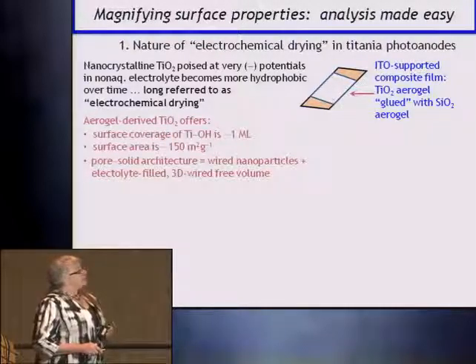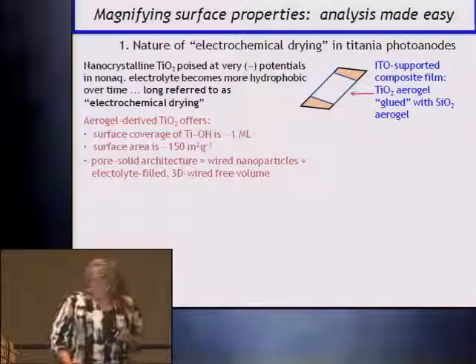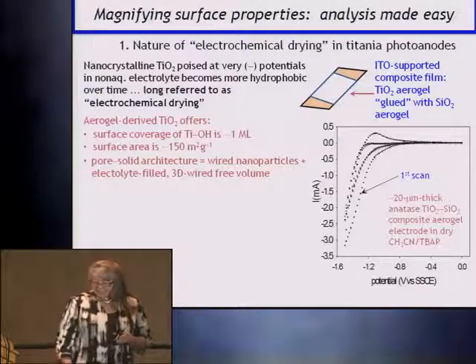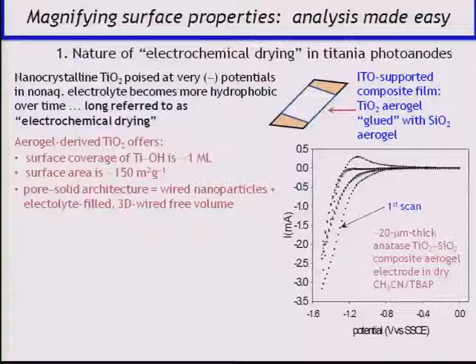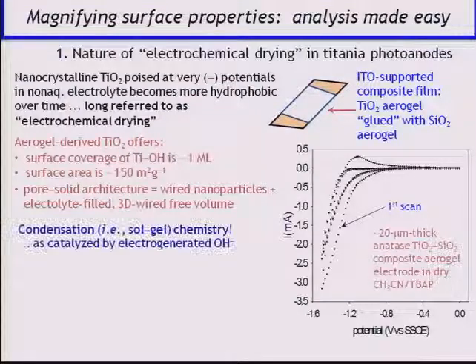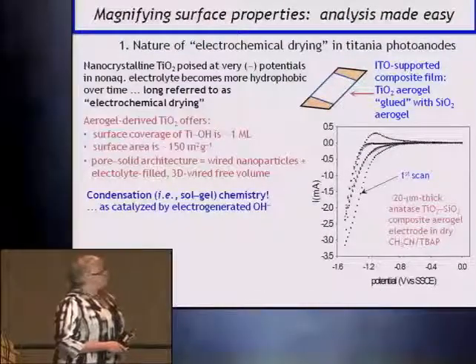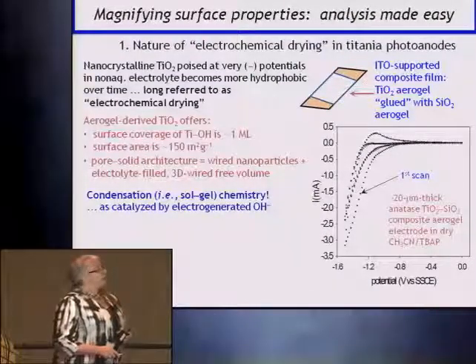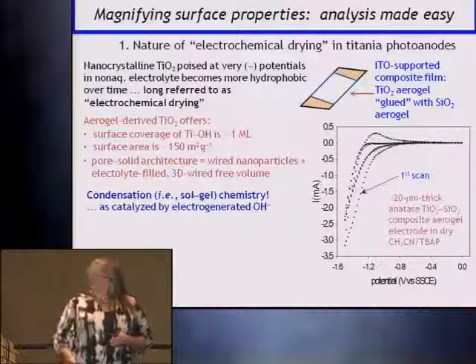Very high surface area, but we've got the architecture. Wired nanoparticles, electrolyte-filled 3D free volume. And just with one scan in dry non-aqueous electrolyte, every electrochemist in this room knows what has happened. Here's the first scan where you're passing a fair bit of charge at very negative potentials. Second scan, there's far less charge being stored at that interface. You've dried it out. It is now hydrophobic. You don't have the same structure of water that is always coming in with those titanols being present. So what's going on is, back to sol-gel chemistry, it's condensation because we've electrogenerated hydroxide by going so negative, and the hydroxide is coming from the water that is coming in with those titanols.